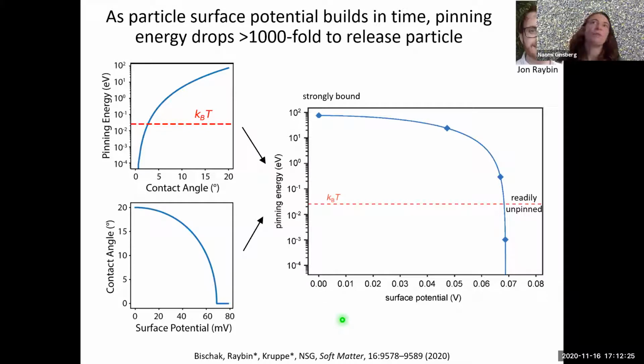Okay, so electrowetting normally refers to what happens to a liquid at a surface when a potential is applied to that surface. But John realized here that the electron beam is generating the potential and that he could combine the dependency of the pinning energy on contact angle and of the contact angle on surface potential in order to determine the pinning energy as a function of the surface potential. So you can think of this increasing scale here in the surface potential as a proxy for the progressive charging in time. So initially, there's essentially close to no charge on the particle, and we estimate that the pinning energy is very, very strong, several tens of eV, or over 1,000 times the thermal energy, kT, at room temperature at least.